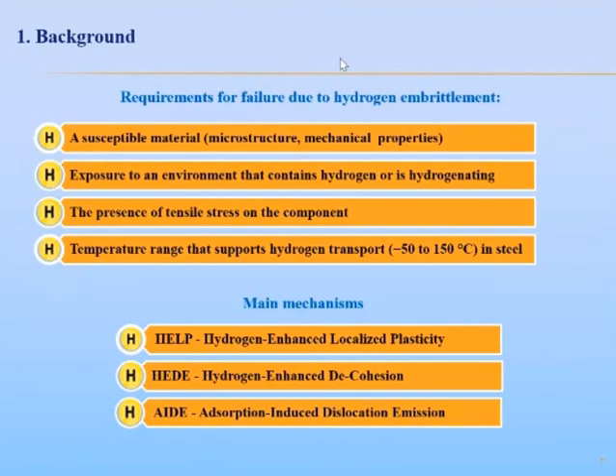There are four requirements for failure due to hydrogen embrittlement, including microstructure, mechanical properties, exposure to an environment that contains hydrogen or is hydrogenating, the presence of tensile stress on the component, and a temperature range that supports hydrogen transport in steel. It's between -50 and 150 degrees Celsius.